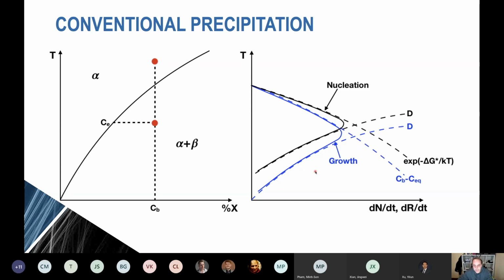And this is absolutely true for precipitation processes that occur in aluminium alloys. This is technologically very important, and this C-type behavior guides the temperatures that we choose to do our precipitation heat treatments in commercial aluminium alloys. Aluminium alloys like aluminium copper magnesium or aluminium magnesium silicon are traditionally given a heat treatment at somewhere between 150 or 200 degrees for between 6 or 7 or 8 hours up to 20 hours to develop the precipitate structures that give us the interesting properties.